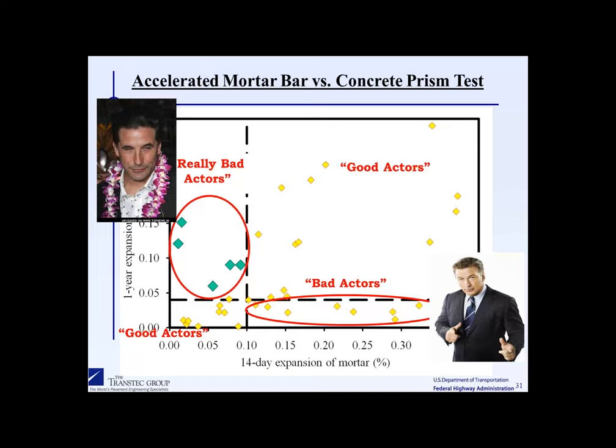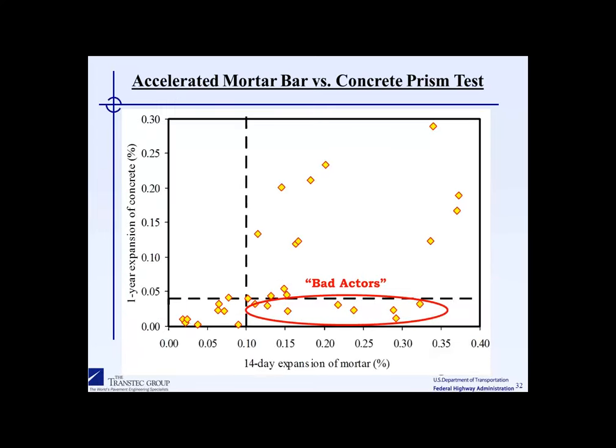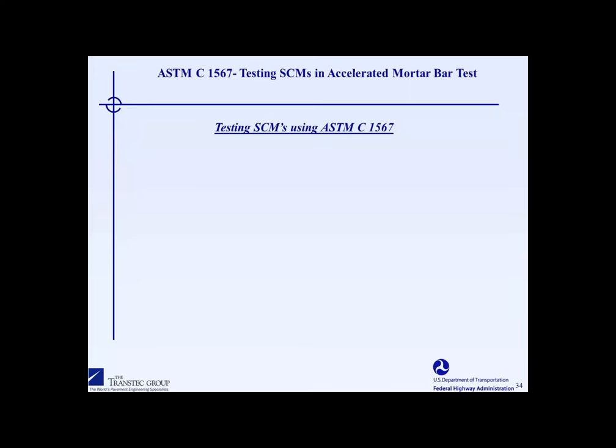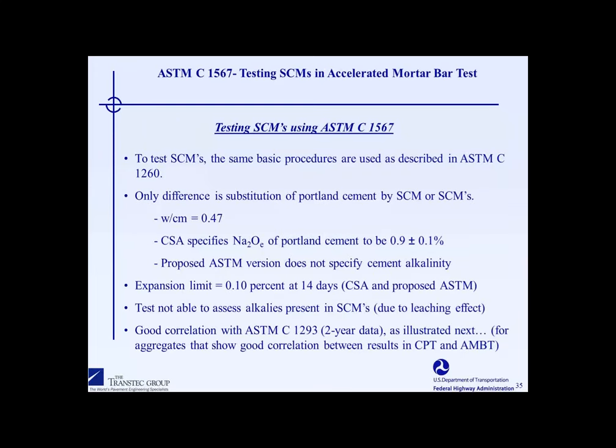Given the time constraints, I won't go into the details much on what's causing this behavior, but what I can say is it almost always occurs with coarse aggregates, and our experience is it tends to be the coarse aggregates that contain chert. It has to do with something known as the pessimum effect, where the relative amount of chert in the aggregate will determine whether or not you pick up expansion in the mortar bar test. We do have a published document that explains this and gives alternative guidance for aggregates that fall in this category. So I just wanted to draw some attention to these aggregates that behave in ways that we prefer that they didn't.